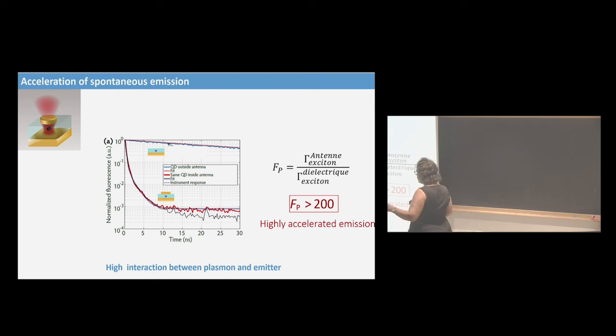When you measure the decay, you excite with a pulse laser, you detect the photons, and you count the time between the excitation and the emission. You repeat this millions of times, over a few tens of seconds, and you can construct this decay curve, which is the intensity of fluorescence as a function of time. This is what is called the decay curve.